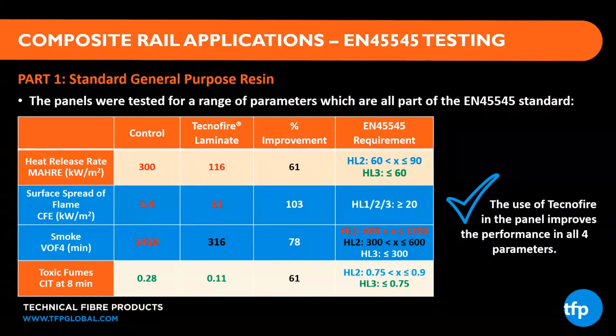The base resin, although it's not FST, doesn't contain any halogen or antimony, so it's not generating toxic fumes. But we're still seeing a 61% improvement. So if we look at that overall, if we look at the percentage improvement column, by dropping in this 0.5 millimeter layer of Tecnofire as a functionalized surface veil pre-vacuum infusion, we've improved heat release, surface spread of flame, smoke and toxicity by 60 to 100%.